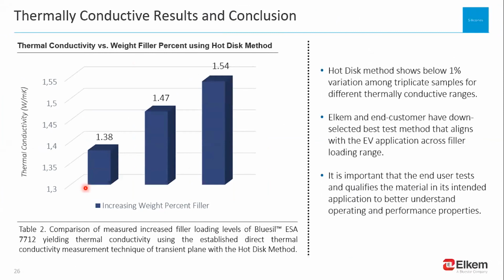Further, it was important to understand the variance in materials within one test method. Table 2 shows the comparison of measured increased filler loading levels of BlueSil ESA 7712, yielding thermal conductivity using the established direct thermal conductivity measurement of transient plane by the Hot Disk method. The results showed consistent outcome with a standard deviation of 0.01 or approximately 1% of triplicate testing.